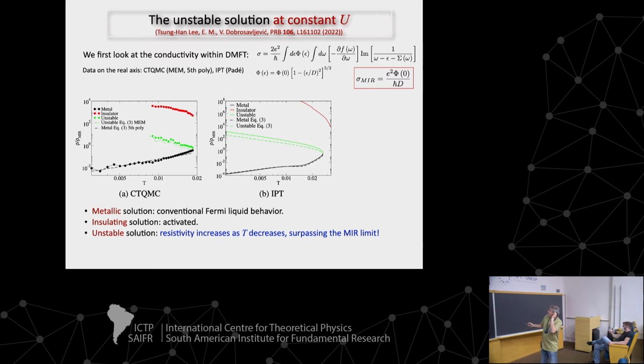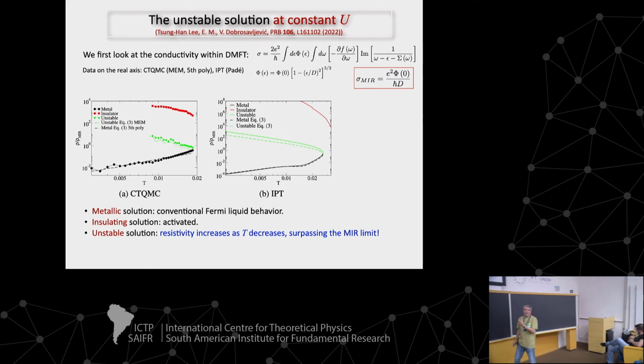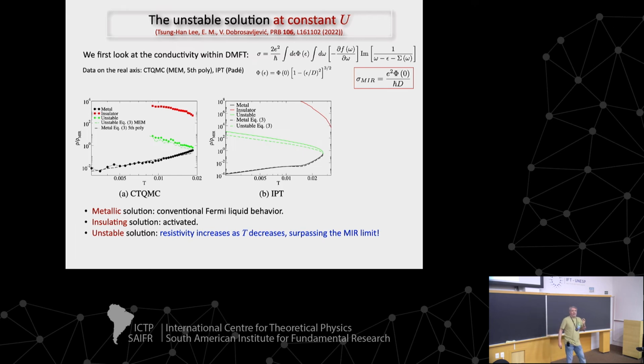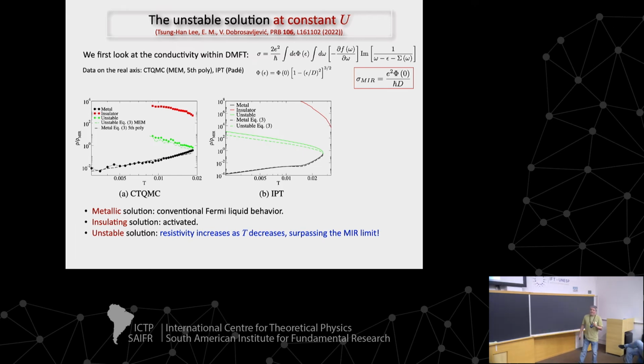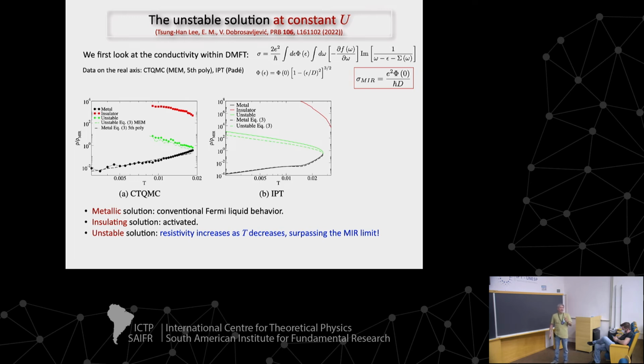There is this thing here that I didn't emphasize too much, the so-called Mott-Ioffe-Regel limit of transport, which means that when the mean free path is equal to the lattice parameter, this is the largest resistivity that you can get in a semi-classical description. So you cannot scatter on a length scale that's smaller than the lattice parameter. And what this shows is that the resistivity in this domain wall matter goes above the Mott-Ioffe-Regel limit, which is a very non-classical, non-trivial behavior.